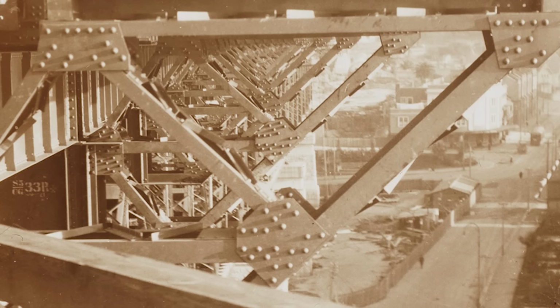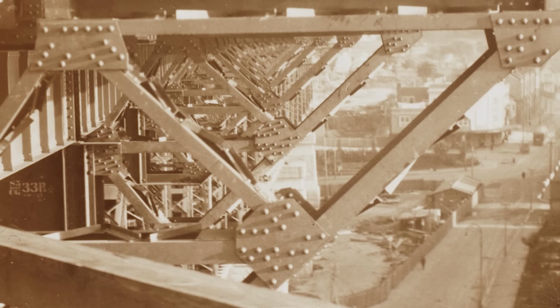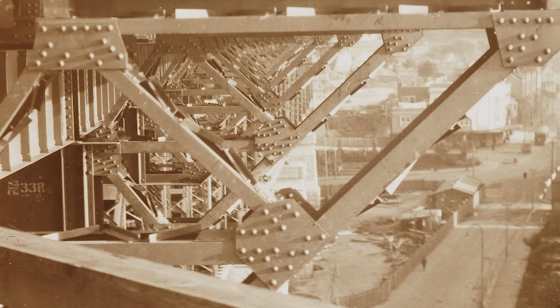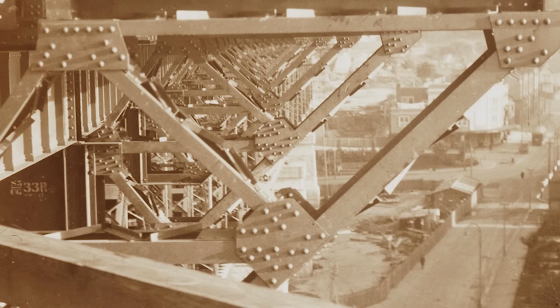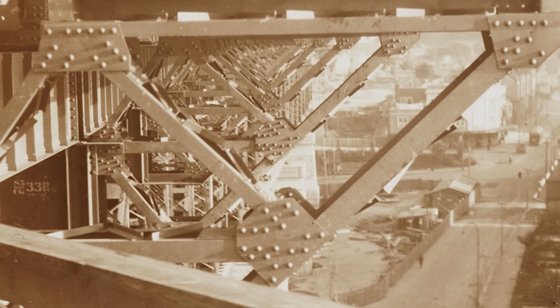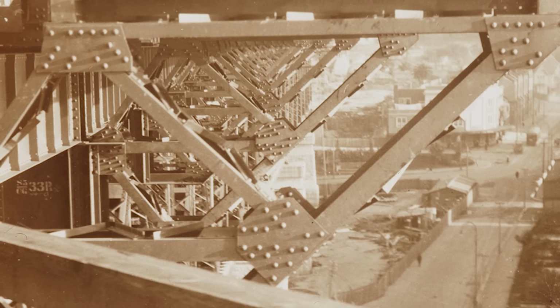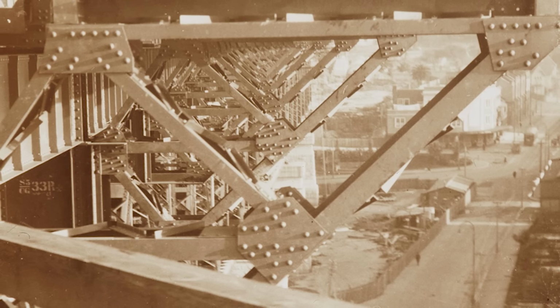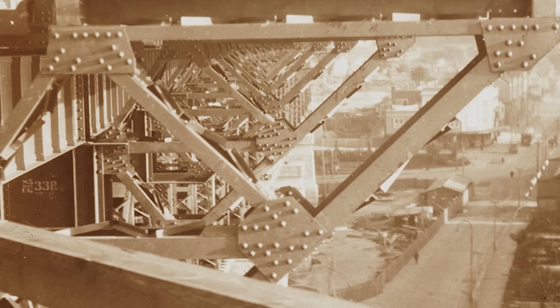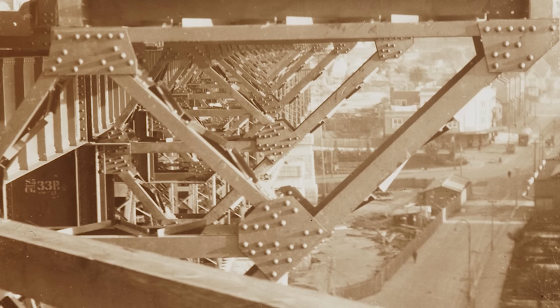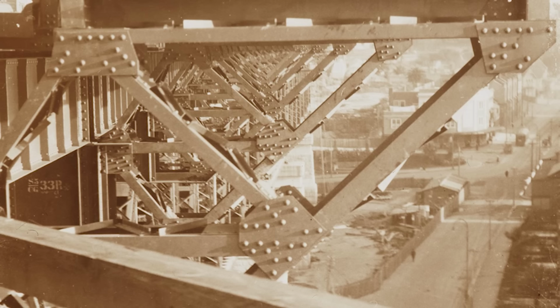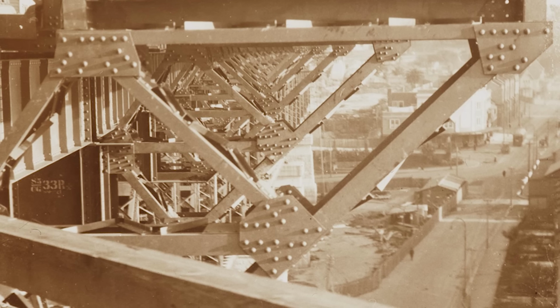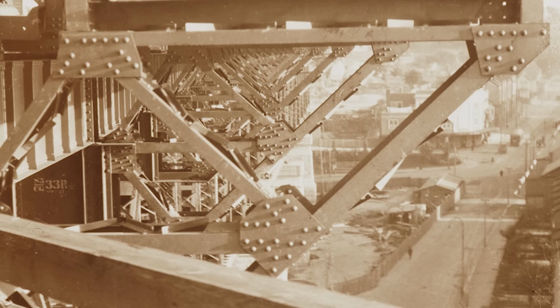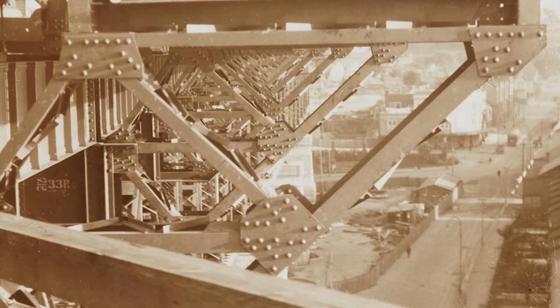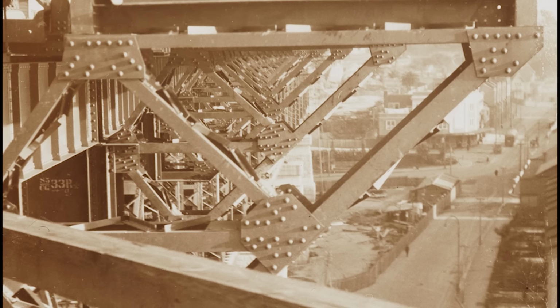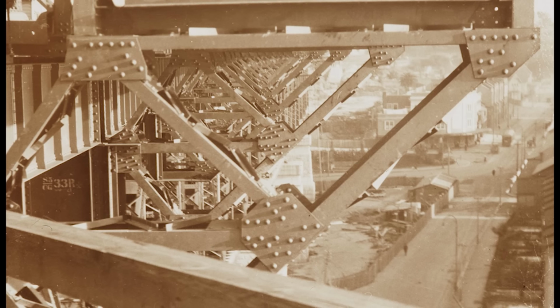But the real genius lay in what happened when things went wrong. Stress concentrations that would propagate catastrophically through continuous welds stopped dead at rivet holes. The drilled opening redistributed load across the surrounding material, preventing the unzipping failures that plagued welded structures. If one rivet failed, neighboring rivets absorbed the additional stress without compromising joint integrity. The redundancy was built into every connection, 600,000 individual fail-safes that made the entire structure virtually indestructible.